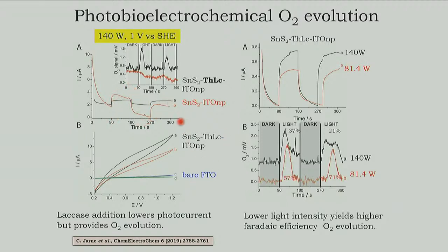This is the illumination signal. We get a photoresponse from the electrode, photocurrents, and we can see here, this is from dark to light, we can get better currents here in the cyclic voltammetry, and this is what our sensor is showing us. It was very, very little amount of oxygen. And also, if we decrease the intensity of our lamps, this 81.4 corresponds to 1 sun in our latitude.